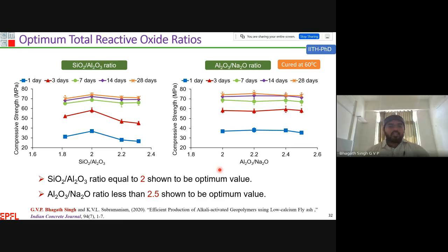And I have mentioned that the total reactive oxide ratios are key to producing similar compressive strength. Then what is the optimum reactive ratio? I have varied the silica to alumina ratio from 1.8 to 2.3 and also the alumina to sodium ratio from 2 to 2.5, with respect to age: at 1 day, 3rd day, and 7, 14, 28 days.